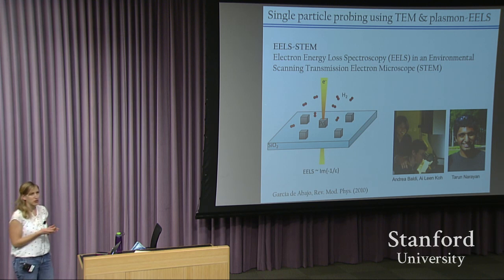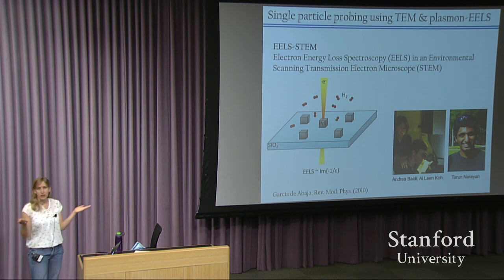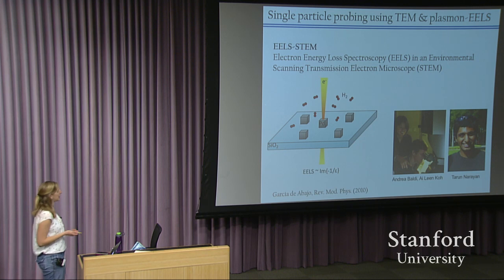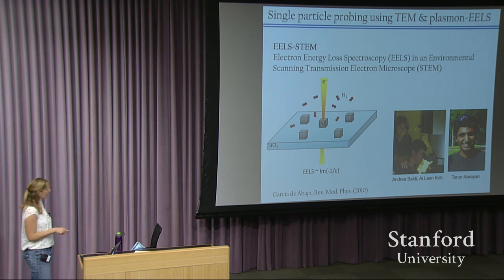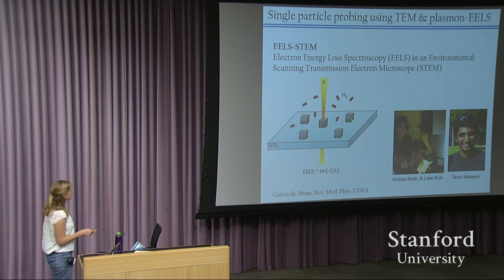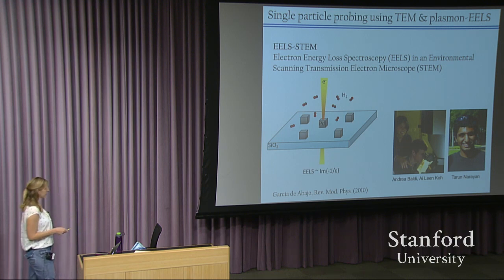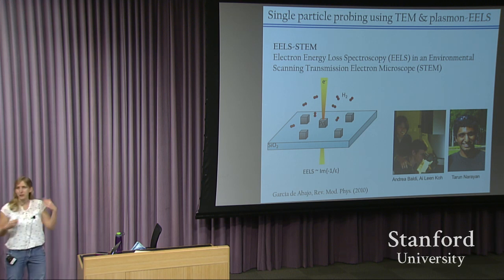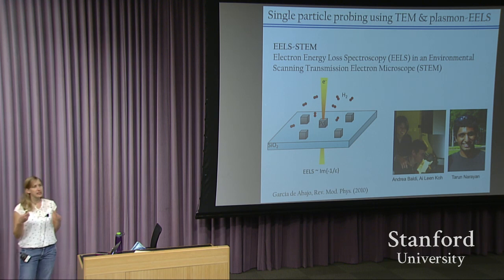You can think about the electron beam as a broadband white light source, but here just focused down, and it allows us to get a high spatial resolution. The electron beam passes through the nanoparticle, and we can use it to image the nanoparticles, but we can also use it to enable spectroscopy. In particular, when the electron passes through the particle, it loses some of its energy by exciting some of the electronic modes in the nanoparticle.